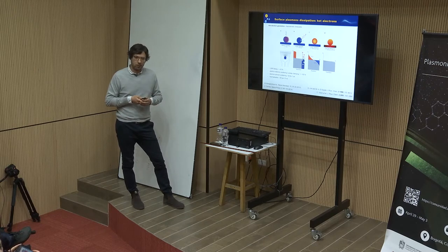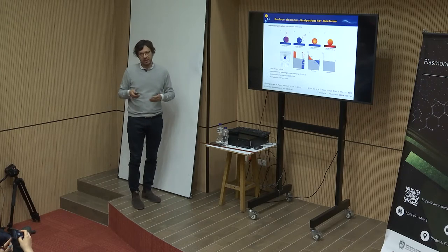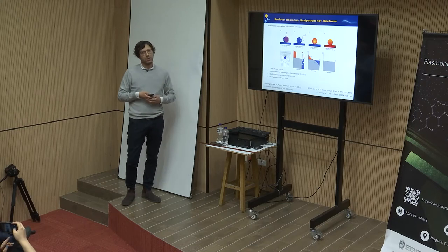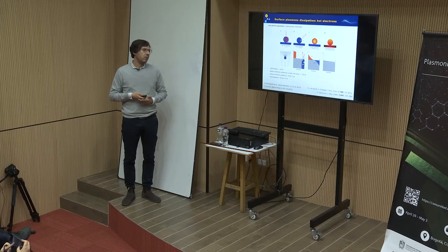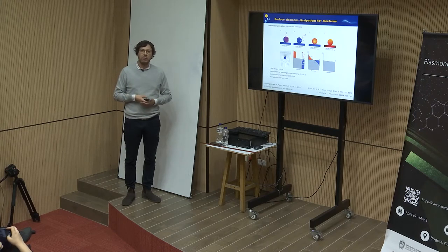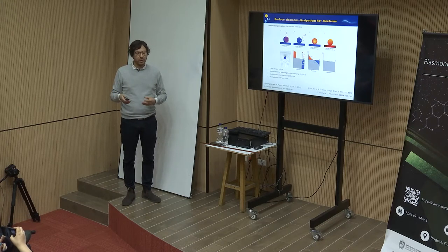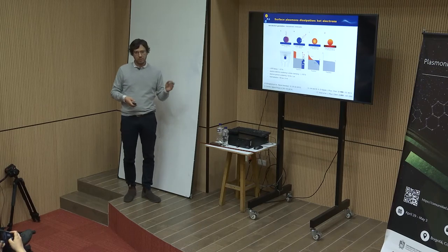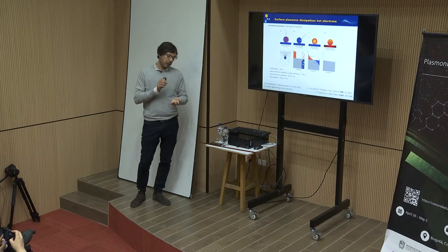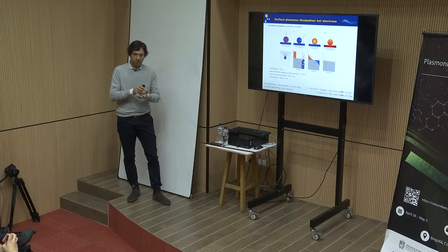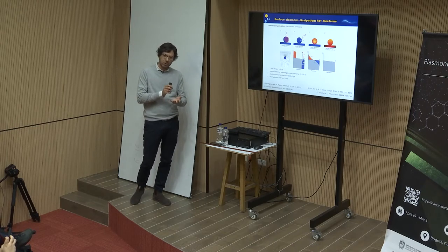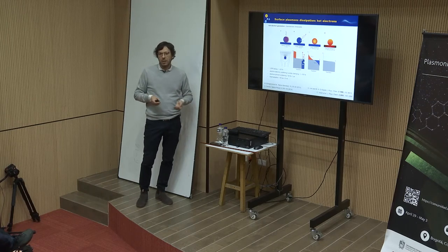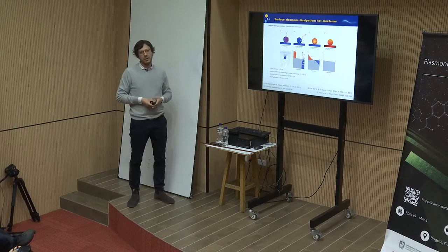What is the order of temperature you can reach? It depends on how much you pump the material. As I show in my lecture, with solar illumination, we achieve more than 600 degrees at 15 suns. But you can reach much higher temperatures depending on how much you pump. If you use a laser, in comparison you have to use, for example, 1 million times more power density to create a similar temperature, 600-700 degrees, on a single nanostructure. I will show later the Brongersma group, who with a laser induced the ignition of aluminum nanostructures because they create a very strong gradient of temperature and reach it in a very few seconds. So this is another interesting point: we can create a really very fast gradient of temperature, which is usually not achieved with other ways of heating the nanostructure itself.